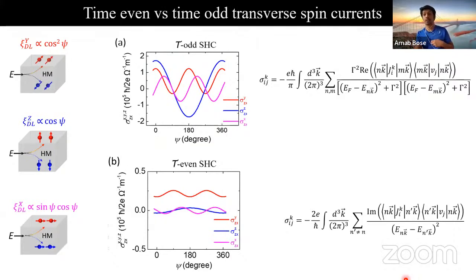Okay, so one more thing before showing the experimental results. We also have done first principle calculations. So we find that there are two sources of spin current, time odd spin current and time even spin current. Both of them originate from the spin split bands. But the time odd spin current is an order of magnitude higher than the time even spin current. And second thing, we need to note that if we have micron size devices with multiple domains, then the time odd spin current can cancel out. However, if we have more than 10% unbalanced domains, we can still have a substantial contribution from time odd spin current, because this is 10 times stronger than the time even spin current.